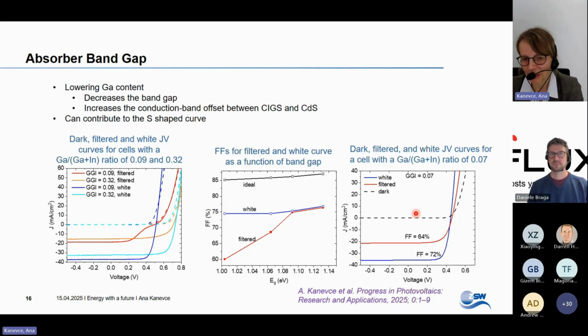Yes, I know from my perovskite colleagues that low band gap perovskites have problems with stability, and CIGS is much more stable. So this is one argument why one would use perovskite CIGS tandem as opposed to perovskite-perovskite tandem. Also, CIGS can go down to 1 electron volt without problem, and this is important when we want to go to triple junction. So those are the two arguments; stability is a big issue.